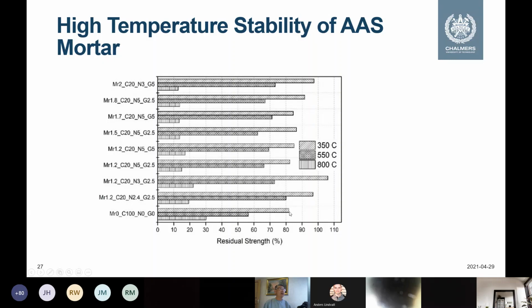Is about 80. But after 800, the residual strength is about 30 for ordinary Portland cement. But for alkali-activated concrete, you can see after 350, the residual strength is higher than Portland cement. After 550 degrees, the alkali-activated concrete is still higher than Portland cement. But after 800, it is lower than Portland cement.